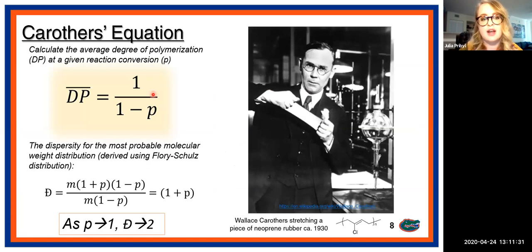This relationship between reaction conversion and degree of polymerization is incorporated into the Carothers equation, which is in this box here. And we can also say something about what dispersity we would expect from a step growth polymerization. We can derive the most probable molecular weight distribution using the Flory-Schulz distribution, which is how you derive this term here. And it simplifies to dispersity equals 1 plus p. So as the reaction conversion approaches 100%, the dispersity value will approach 2. And in this picture here, I have Wallace Carothers, whose namesake equation is on this slide, stretching a piece of neoprene rubber back in 1930.